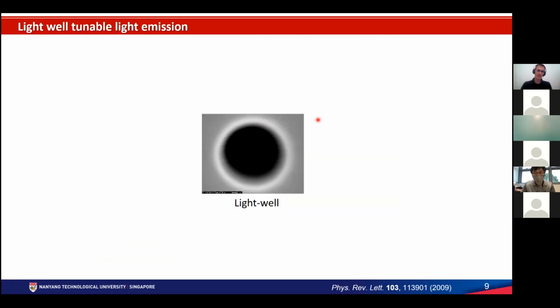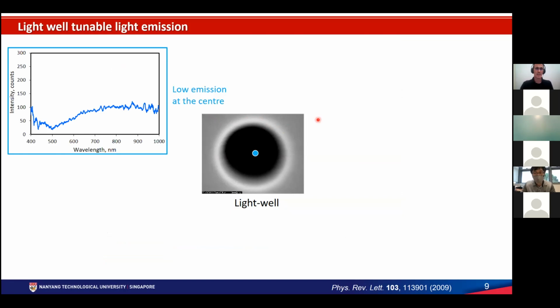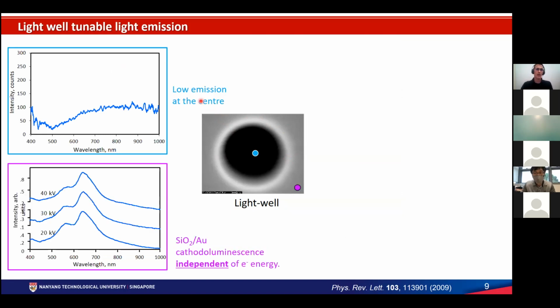And we identified mainly three emission areas. The center of the well, or around the center, has low emission. Ideally you should have no emission, but you have a little bit coming probably from material left at the bottom of the well. Then you have another area of emission around the well and also very far away from the well. As you can see, there is no change when you modulate the electron energy. The peaks stay at the same position, and this is basically luminescence from the material components, gold and glass.